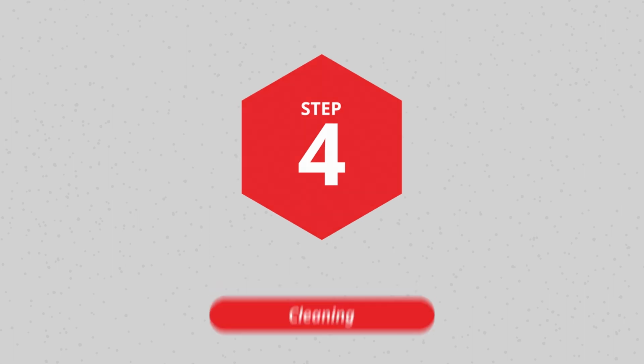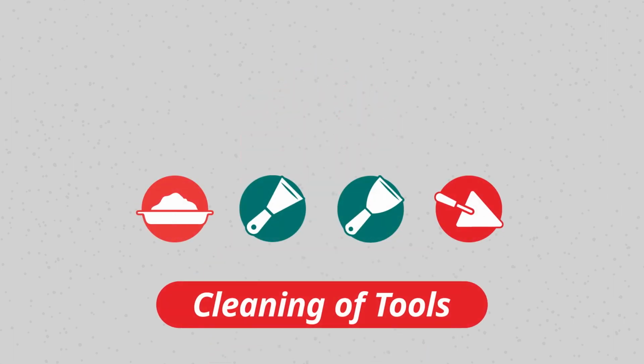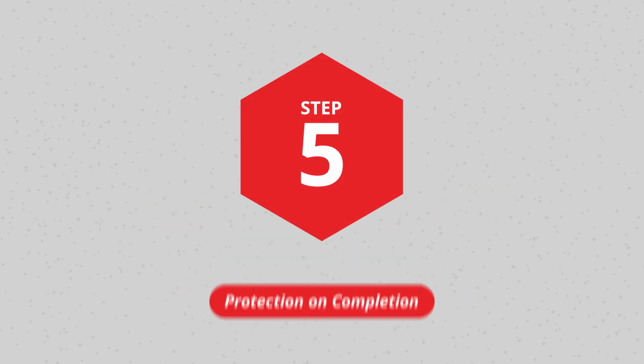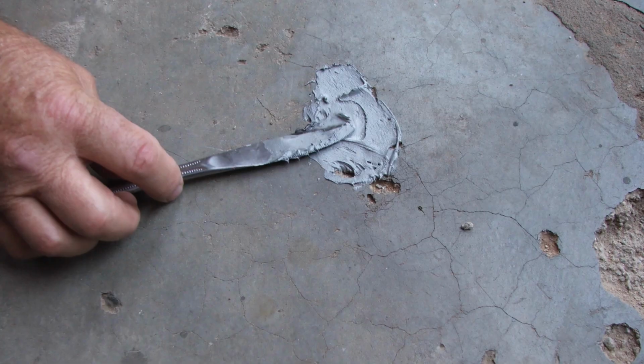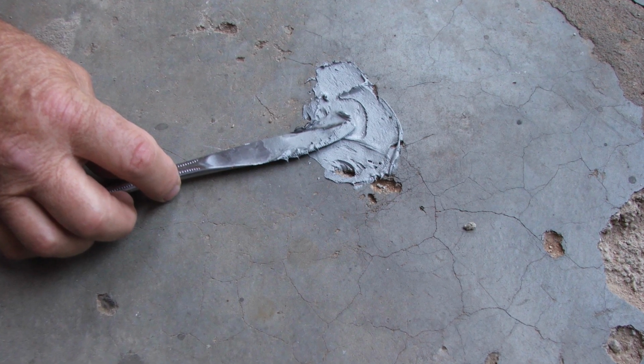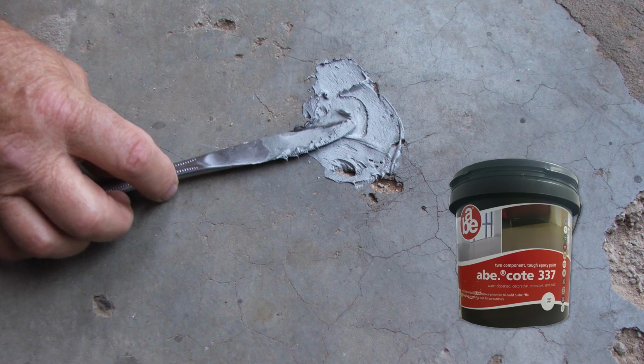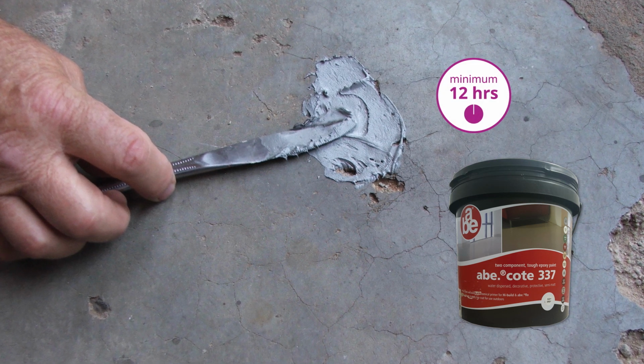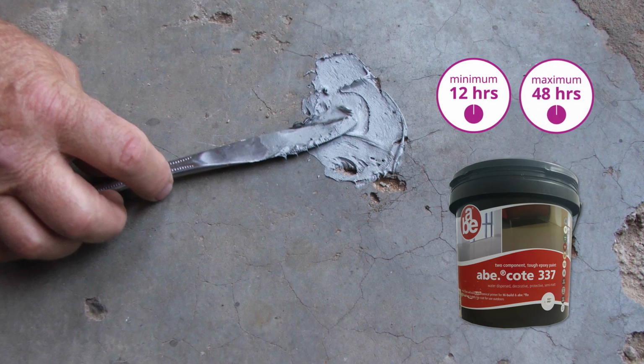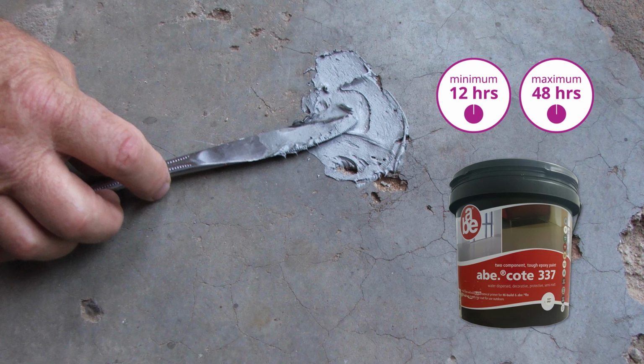Step 4. Cleaning. Tools and mixing equipment should be cleaned immediately after use and before material has set with ABE Superbrush Cleaner, followed by washing with soap and water. Step 5. Protection on completion. If used as a filler and an epoxy coating is required, allow a minimum of 12 hours and a maximum of 48 hours before commencing with the epoxy coating.